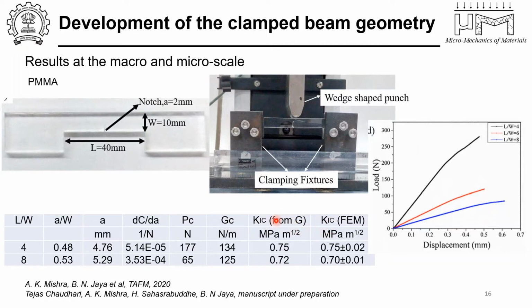And the K1C that we get from the G and the K1C that we get directly from our normalized solutions also match very well. And this value of about 0.75 to 1 MPa root meter is what is reported for PMMA also in the literature. So this led us to get confidence that this particular geometry works very well for macro scale as well.